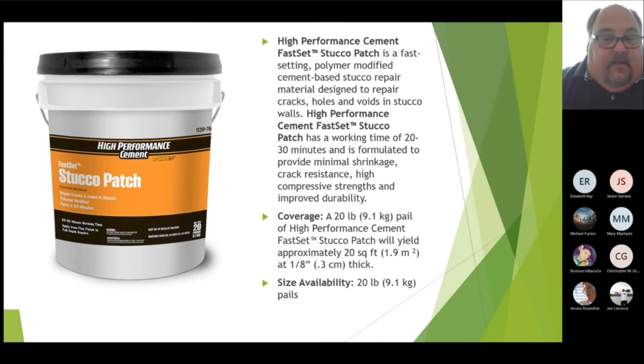It's polymer modified, so you don't need to add a separate bonding adhesive or any type of fortifier. You just need to make sure you scrub it with a wire brush, make sure all loose debris is off, that it's damp, and it's got about a 20-30 minute work time. You want to use this for patching. It's fantastic because you can go over it and paint it with a water-based latex paint in 2 hours. So for guys that are on the job, you can put this in your truck, go do your stucco patch, hit lunch and come back, paint it and go home. You don't have to worry about waiting for it to cure to come back to paint it. So that's fantastic. It saves time, saves money. It's an incredible product. I'll give you a little hint too.